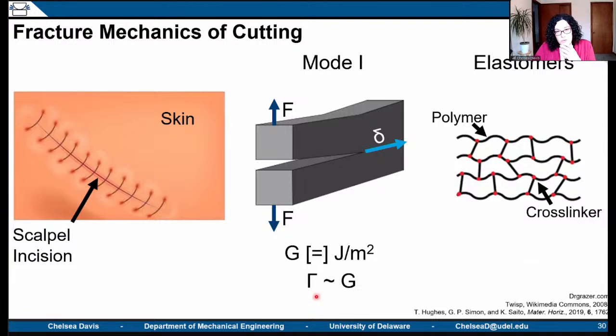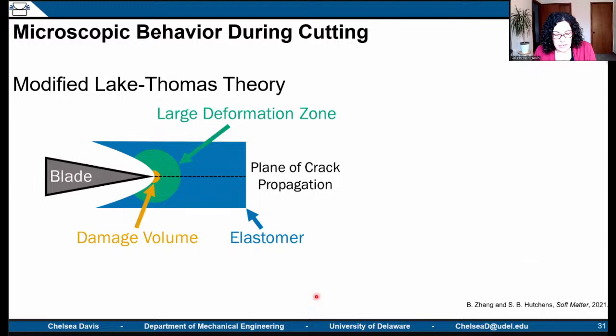And for elastomers, what we're focusing on cutting is a polymer network that is cross-linked or reacted at different sites and tied together into effectively one single macromolecule, right? So the Lake Thomas theory is a theory that was developed many years ago that effectively said the energy required for cutting is the energy required to break a plane of molecules that your crack has to propagate through in these systems.